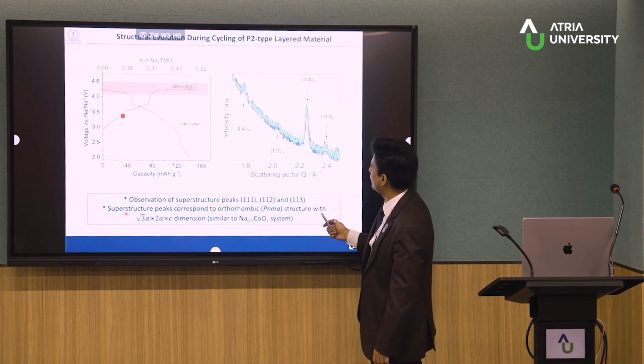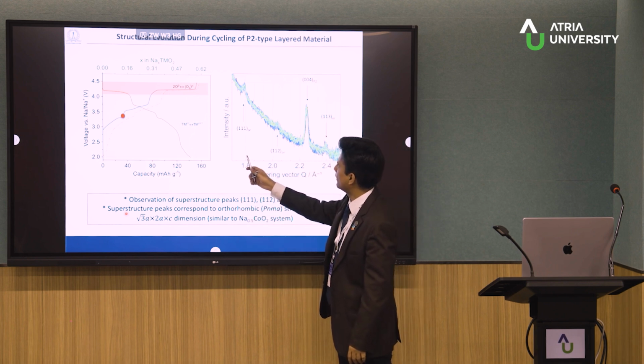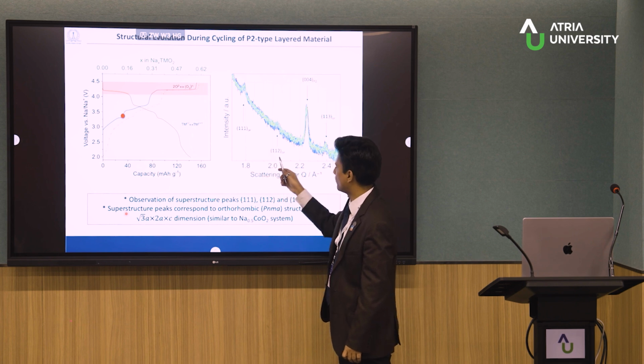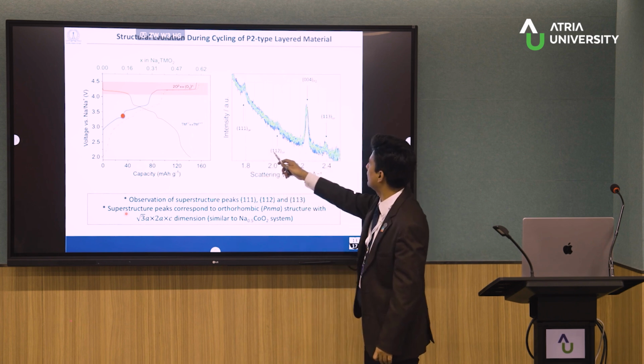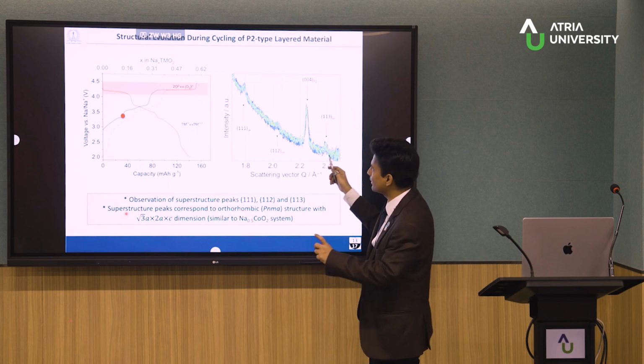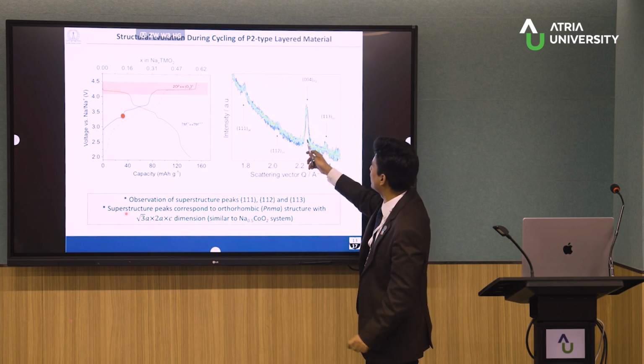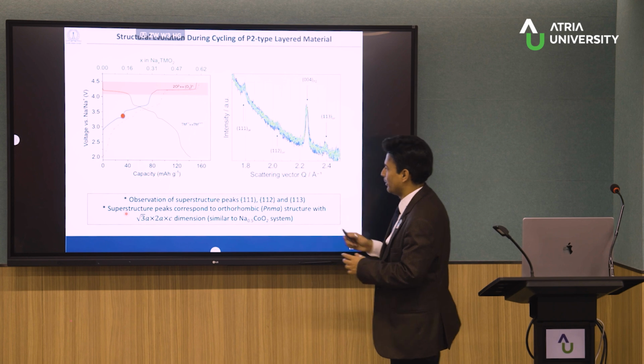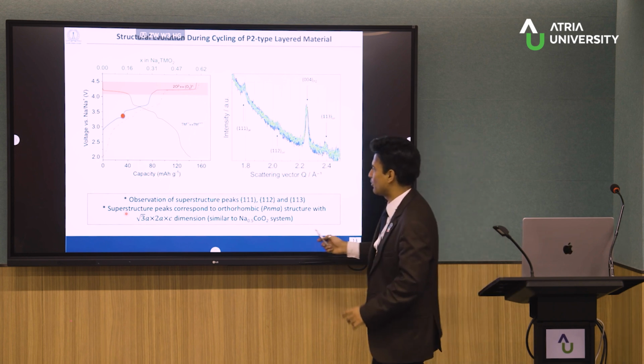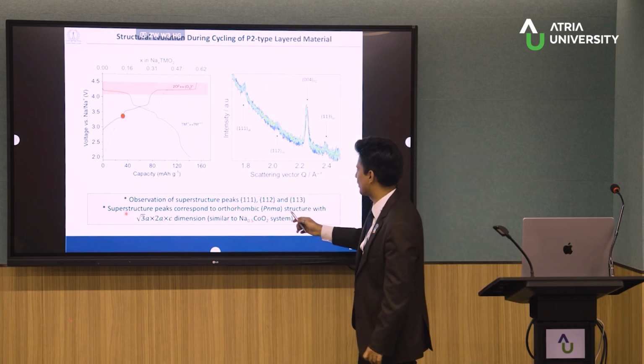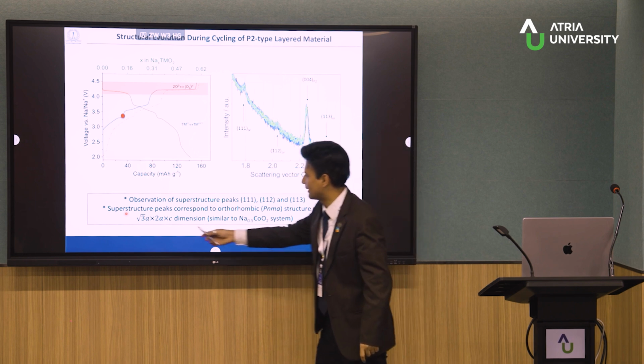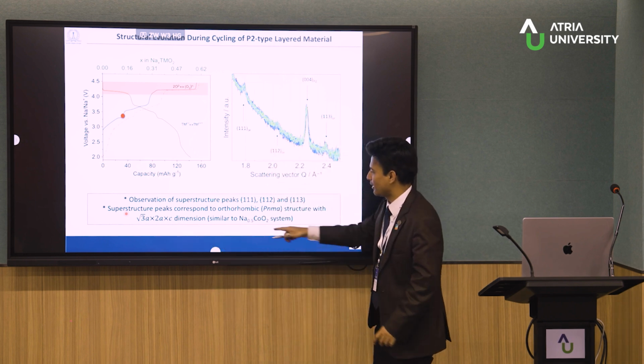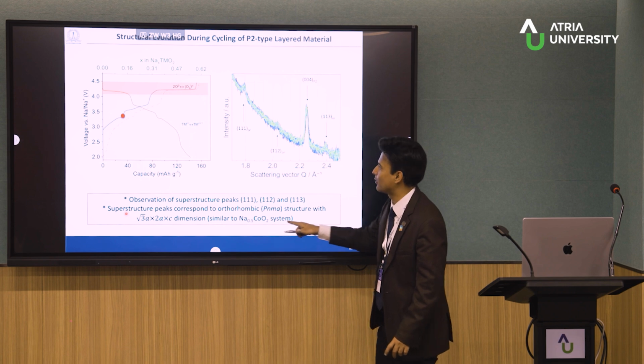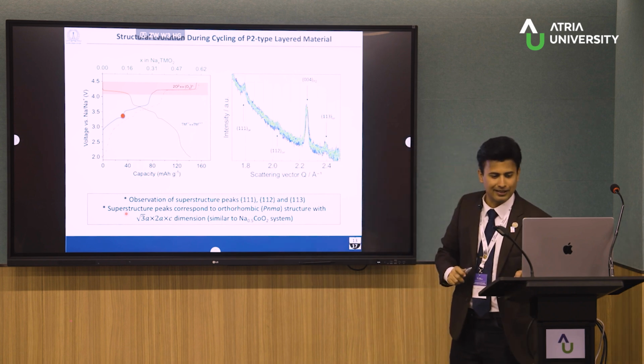So here, if you see, these are the 111, and there is a small amount of new peak, 112 and 113. These are the typical superstructure peaks which appear on close observation, and this is our typical P2 kind of material. Even if there is the orthorhombic structure, there is a superstructure peak with this kind of dimension, which is very similar to different NaxCoO2 kind of systems. Many layered systems have the same thing.